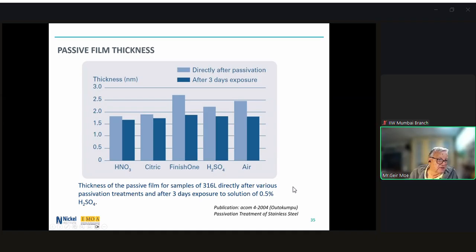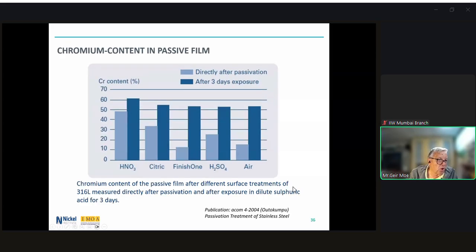Avesta also measured the thickness of the passive film directly after passivation and after exposure to dilute sulfuric acid for 3 days. Initially, there were differences in the thicknesses. We can see that in the light bars directly after passivation. But after 3 days, the thickness of the passive film for all three treatments were similar. Avesta also measured the chromium content of the passive film. Again, there were differences in the chromium content directly after passivation. You can see here between nitric, citric, FinishOne, sulfuric acid, and air. But after 3 days, the chromium contents of the passive film for all three treatments were very similar.